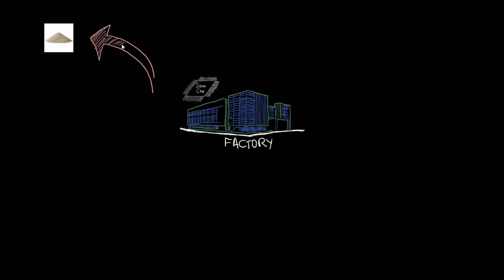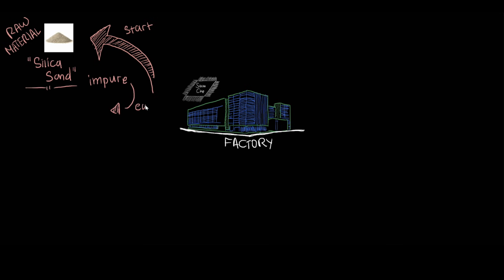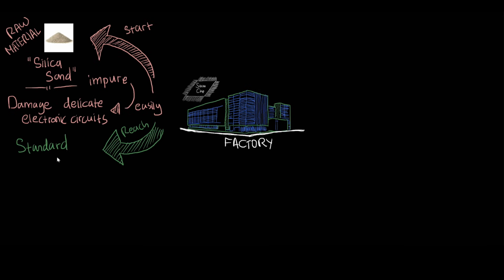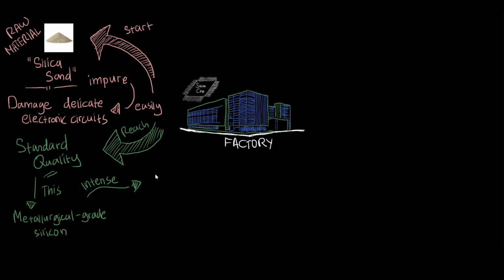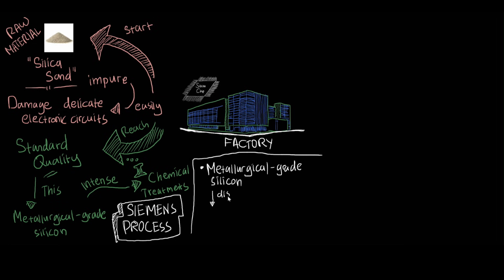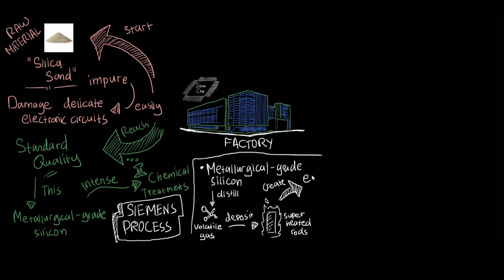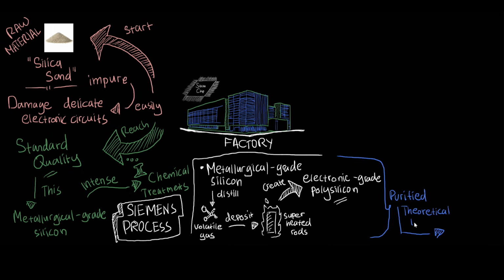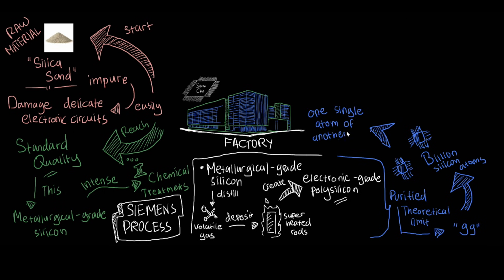The fabrication process starts with the raw material, which is usually silica sand, but this natural substance is full of impurities that would instantly ruin a delicate electronic circuit. To achieve the necessary quality, we have to refine this metallurgical-grade silicon through a series of intense chemical treatments known as the Siemens process, where we distill it into a volatile gas and then deposit it back onto superheated rods to create electronic-grade polysilicon. This resulting material is purified to an almost theoretical limit, often described as 9 nines purity, which means that for every billion silicon atoms, there is less than one single atom of anything else.